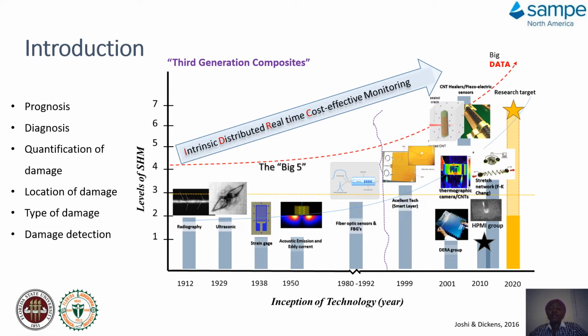And 2020 target research is focusing on big data, in which we've been able to add to the achievements of this technology, which is a third generation composite. In that way, we can easily diagnose the material, check for the quantification of the damage, which is if the damage is high or if it's low, and easily locate where the damage is and the kind of damage which the composite is exhibiting, and also detect the damage easily without complete destruction of the material.